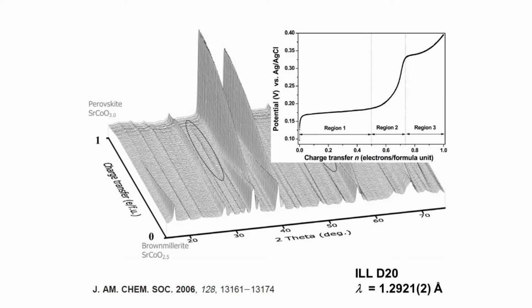This means that immediately the first oxygen that goes there forms a small fraction of the strontium cobalt oxygen 2.75, and we have the remaining part that still has the brownmillerite phase. Of course, the fraction of these two phases changes in time till we reach the complete strontium cobalt oxygen 2.75, which is a deficient cubic perovskite. And we will see this better from the Rietveld refinement in the next picture.